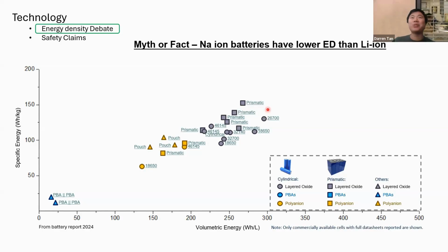But what's surprising is when we put LFP on this plot. So when we consolidate the state-of-the-art LFP, you look at the BYD Blade battery, you look at the CATL prismatic, you look at the highest energy density 32700s, the 21700s, and even the 18650s. You can see that by looking at specific energy density, a lot of claims of sodium ion are not that far from LFP. And some of them are already encroaching on where LFP is.